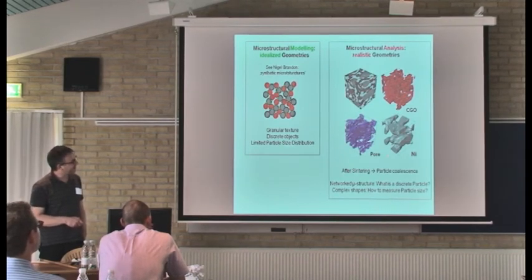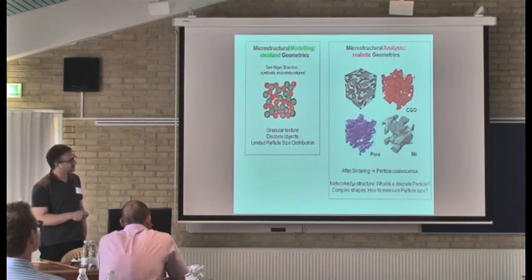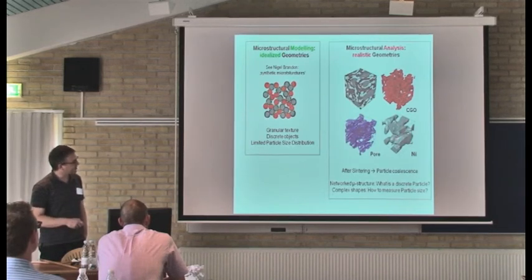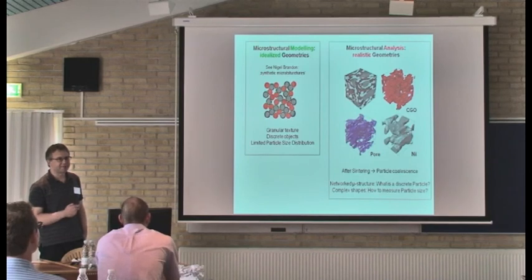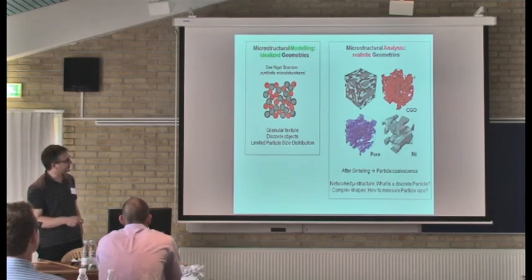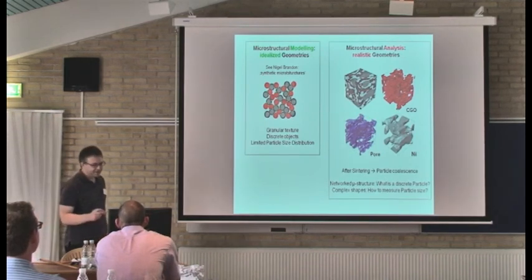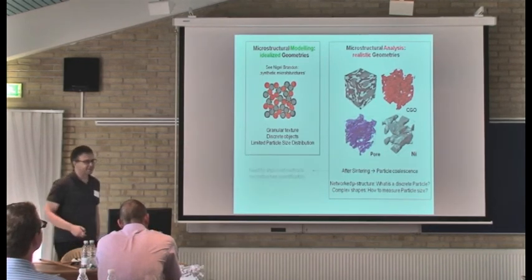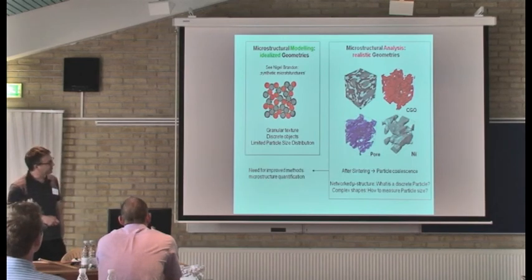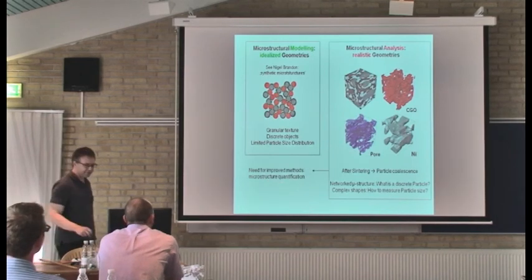First of all, after sintering, we do not have these discrete objects anymore. We lose the information about where the primary particles are. We have a network of microstructures, and it is quite difficult to say what is a particle. The question then arises: how do we measure particle size? This is one example which shows that we need improved methods for microstructure quantification.